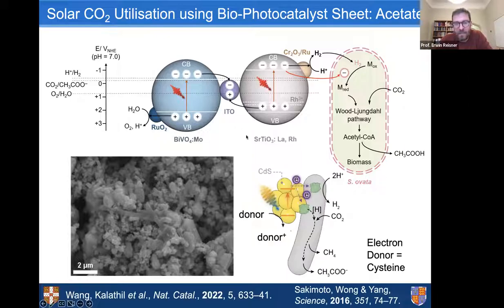And this may look familiar to a previous publication, in this case here from Peidong Yang. So what Peidong Yang's group did before was sensitizing Moorella, another bacterium that has a similar pathway, with cadmium sulfide. And by photoexciting cadmium sulfide, also it was shown that CO2 could be reduced to produce acetate. However, there's one significant difference between these two systems, and that's that the previous report uses cysteine as an electron donor. And in this case, of course, you have to feed in cysteine as a sacrificial reagent, whereas we are actually extracting electrons from water to make oxygen. And also it is now known that the cysteine is significantly metabolized as well to produce acetate. So it's not clean conversion in this case for CO2 to acetate, there's co-consumption of cysteine to produce acetate.